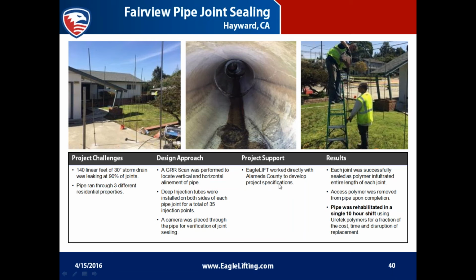So instead of digging everything up, a GPR scan was performed to locate the vertical and horizontal alignments of the pipe, and then the deep injection was performed at depth in order to seal, densify, and lift the pipe back to level. So each joint was successfully sealed as polymer infiltrated the entire length of each joint. They used a camera to watch this process happen, and then any excess polymer that did infiltrate into the pipe was actually removed upon completion. The pipe was totally rehabilitated in a single 10-hour shift.